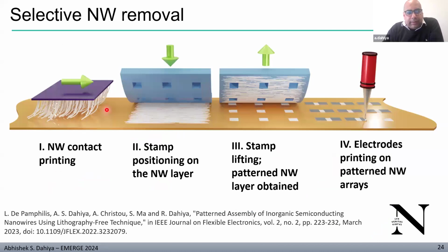In the selective removal, it's a reverse of that. So once you print everywhere, if you can remove the wires rather than pick and place, that will give you a higher yield. In terms of yield, this technique is better. Then you bring a PDMS stamp which has grooves rather than pillars, and in the area which has grooves the wires remain, and the rest can be removed from the substrate.